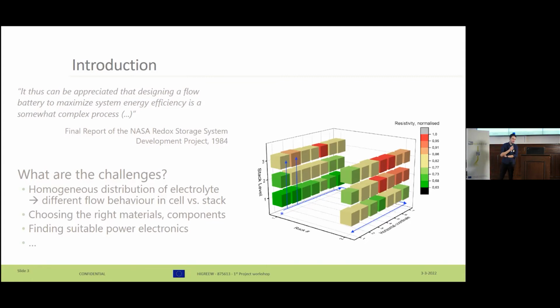But of course, it's also about choosing the right materials. You have to take care of not only choosing materials that are stable when they come in contact with the electrolyte, but also materials that don't degrade the electrolyte itself. So, for example, in vanadium, you have to take care to not use any metals, because then you can destroy your negative electrolyte.